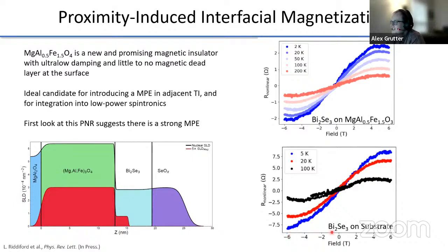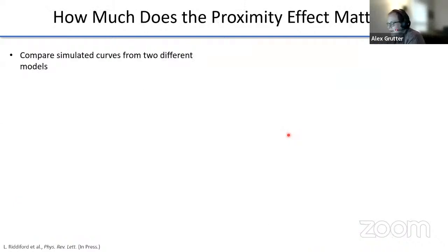So then she decided to check what you get from the transport data when you just grow bismuth selenide on a bare non-magnetic substrate. And the awkward answer is you get something that looks basically the same. So that's a little concerning. And what she then does is try to understand this data and fit it using a two-band model of the conductivity where you have multiple contributions to the Hall effect. And in fact, this fits the data perfectly. And so now we have a problem.